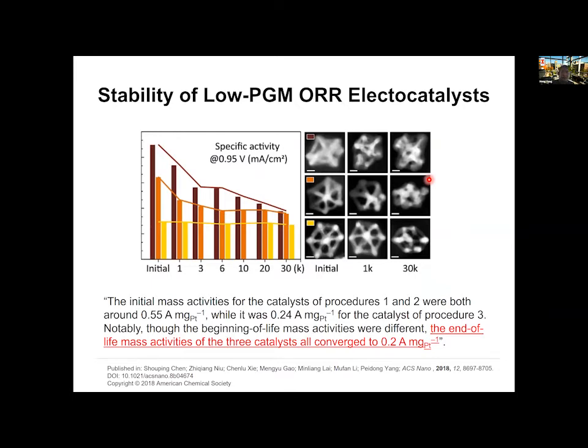This is one of the examples. For instance, the nanoframe I showed earlier has very high activity. But if you run this catalyst at a normal reaction condition over just, let's say, 30,000 cycles, it's almost reduced to the level of platinum, barely higher than pure platinum. So that tells us a story about the need to really improve the durability, since the activity is already quite high in terms of the rotating disk electrode system, i.e. the intrinsic performance of the catalyst.